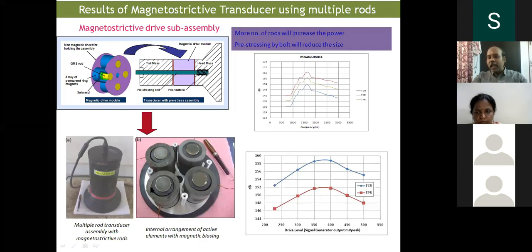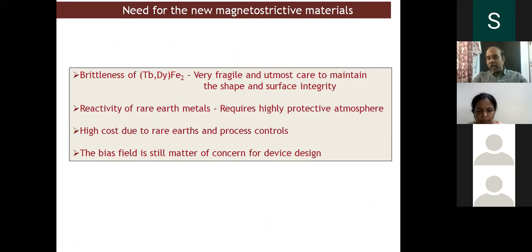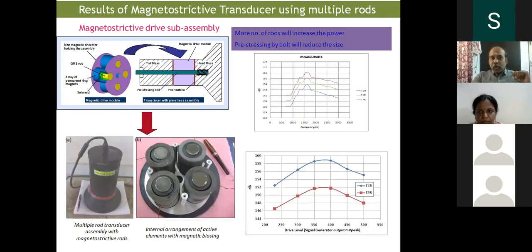We measured the ultrasonic waves produced under the water with a piezoelectric transducer, and it is found to show a high response around 1 kilohertz. 1 kilohertz is a low frequency. It is very important because at high frequency, the attenuation of waves will be more. So this works in the case of a low frequency transducer, and the output was found to be around 172 decibels, which is the actual requirement of the users. So in this material program, not only could we develop the material, we have also ensured that this material is being used at some user level, and these user trials are being undertaken.